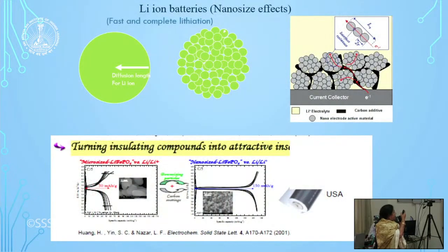So here you can see, as I said, the nano size is very useful because its diffusion length is lower compared to a micron-sized particle, and that helps. You can see over here, a micron-sized lithium iron phosphate. These are called charge-discharge curves, for those who do not know, for a battery. And when you use a nano-sized lithium iron phosphate, you can see a very good charge-discharge curve, and you can see 150 milliamp hour per gram. Whereas here with micron-sized particles, 50 milliamp hour per gram. So you can see a 3 times difference in the performance of the battery when you use nano-sized particles.